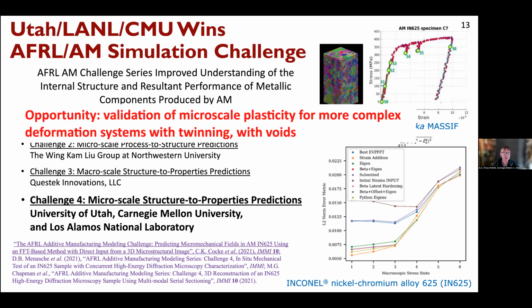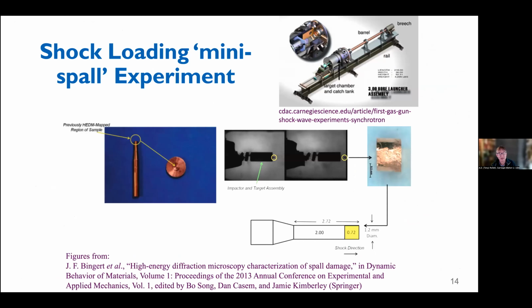Okay, so I will continue on to revisiting some history, if you like, or at least an experiment done a few years ago. And when I retrieved this particular set of slides, I was very pleased to see that there was a picture up here in the top right of not the actual piece of apparatus that was used, but something very closely related that was actually done by your center, Russ, in other words, CDAC, and it was a miniaturized spall experiment. And so John Bingert and colleagues at Los Alamos did a very similar experiment in which they mounted the sort of canonical millimeter cubed inside a bigger piece of copper. That's the piece in here, so that they could then embed it in an impactor and target assembly and do a partial spallation experiment.